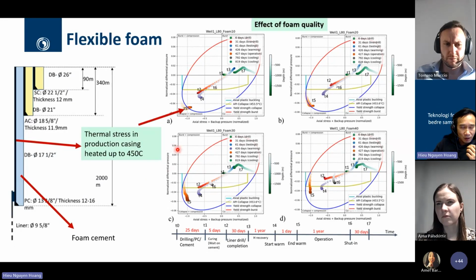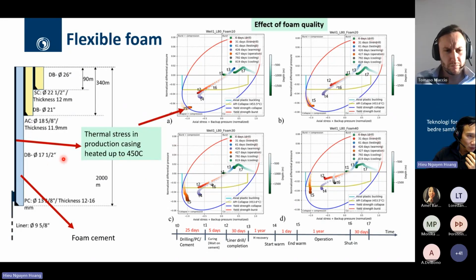And in this figure, I would like to show the effect of foam quality on well integrity in terms of the thermal stress in the production casings. As you see here, the dotted line is showing the thermal stress of the production casing when we are heating up to the temperature of 450 Celsius, in the configuration where we are using the foam cement to cement the production casing. As you can see, when we increase the foam quality to increase the flexibility, we managed to reduce thermal stress in the production casing to within the acceptance limit defined by the API curve, and minimize the risk for